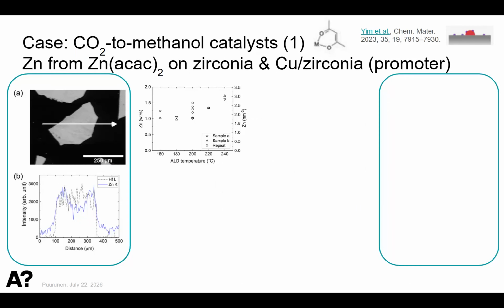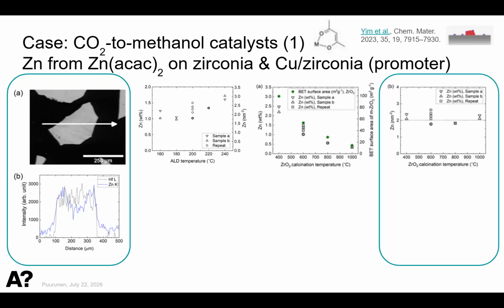Another example is from our rather recent work from my group. We have added zinc on CO2 to methanol catalysts, where we first added, well, this is still about zinc on zirconia. Next one is about catalytic results. So we developed a new process, zinc acac and air oxidation at higher temperature on zirconia. We have taken SEM EDS cross sections to see that the zinc actually goes through the zirconia. Here we show the signal of hafnium to show the support. Zirconium and hafnium always go together, and we show here how much zinc we have obtained as a function of ALD temperature.